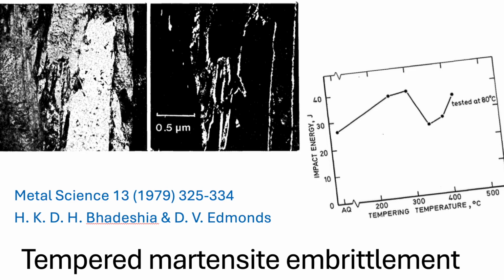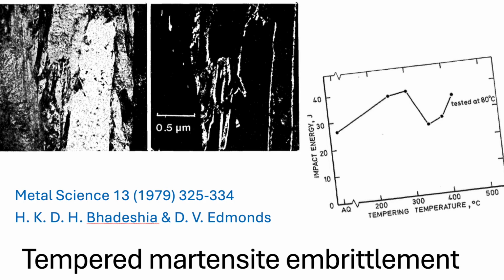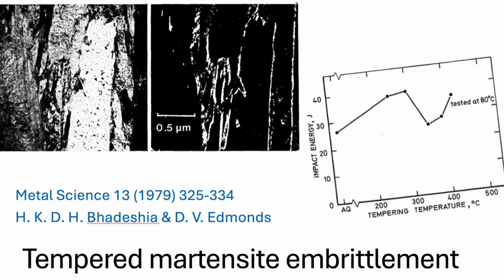Precisely. This microstructural observation confirms it. It shows that those newly formed cementite films are providing the nucleation path, the initiation point, and essentially the easy road for the crack to travel along. So the crack starts, and instead of having to fight its way through the tougher martensite structure, it just follows the path of least resistance, which is the brittle cementite film sitting right there at the lath boundary. It directly links that microscopic structural change, the cementite film formation, to the macroscopic brittle failure mode.